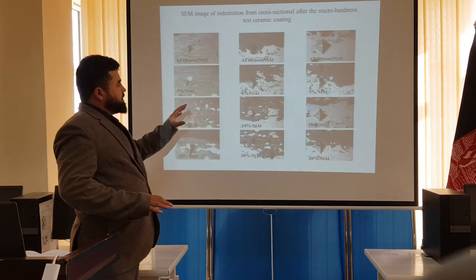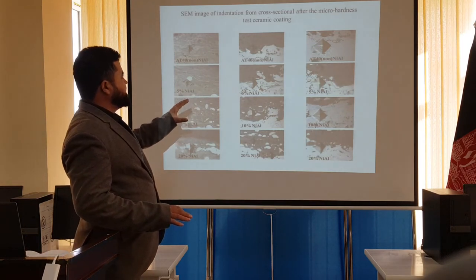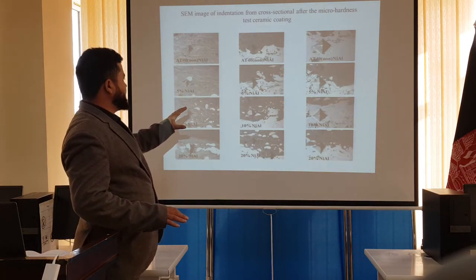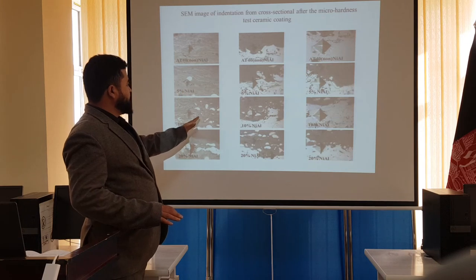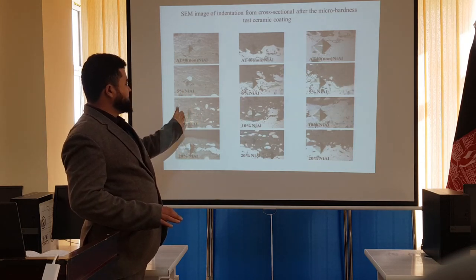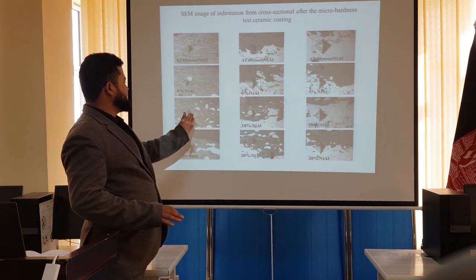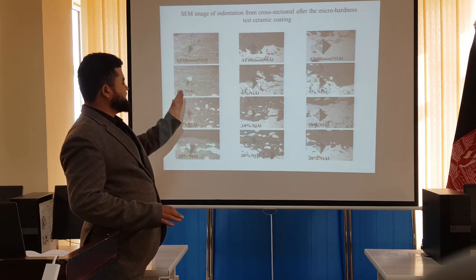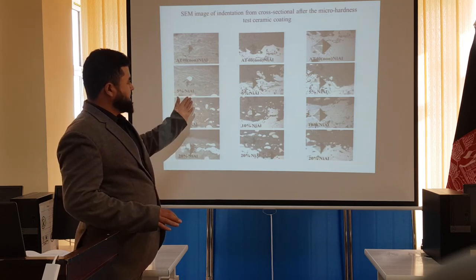This SEM picture we got after the Vickers hardness test. We start from the substrate and the interface between substrate and bond coating, then go to the bond coating and the interface between bond coating and top coating.